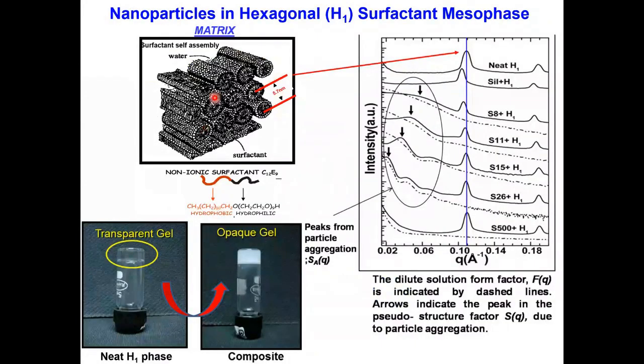Now, these nanoparticles can be put in the surfactant systems, the cylindrical micelles which I was talking to you about. When these micelles are pure, stacked next to each other, they form a transparent gel. But when I put nanoparticles into it, they can form these opaque gels. And this opaque gel forms because the nanoparticles are aggregating within the surfactant.